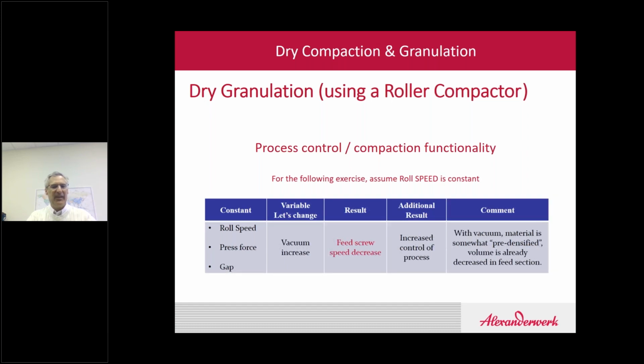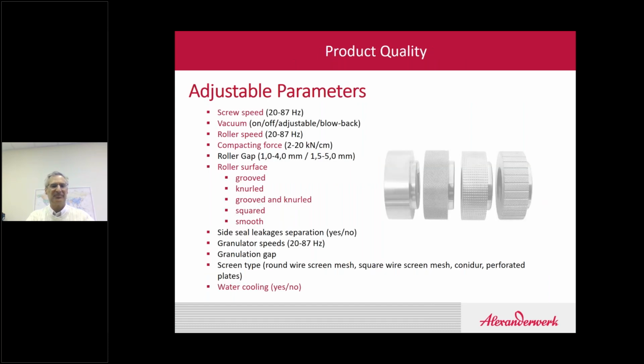Last one, let's assume roll speed, press force, and gap is constant, but I increase my vacuum. What actually happens when I increase my vacuum is the feed screw doesn't have to work as hard. So the feed screw speed is going to decrease somewhat. That gives me actually a better control of the process, which is why Alexanderwerk machines typically run vacuum at relatively high levels, 0.7, 0.8 bar negative.